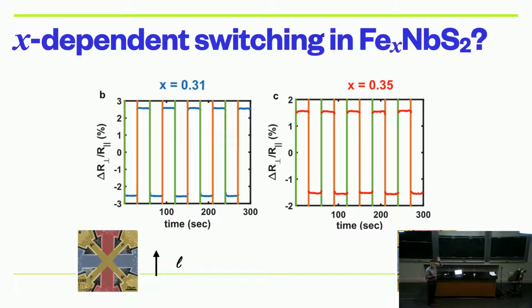What's that? They're out of phase. Yeah, they're like 90 degrees out of phase, basically. What was a low resistance in this one is a high resistance in this one, even though we're pulsing along the same crystallographic directions. How can that be? We're putting current in the same direction. The spin is being imparted in the same direction. What is changing is just that small change in the percentage, just a few percent, in the intercalation. And it's like we're rotating the magnetic order in opposite directions. It doesn't make any sense.